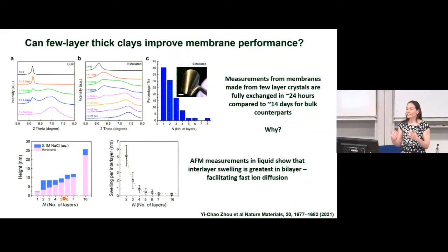And that effect is decreased, and we've done some density functional theory calculations to be able to understand the difference in the interaction and what happens when you start taking layers away from the structure. And that's supported by this strength of interaction, that the interaction between the layers is much greater. And this behavior then tends towards the bulk when you're getting up to 7, 8 layers.